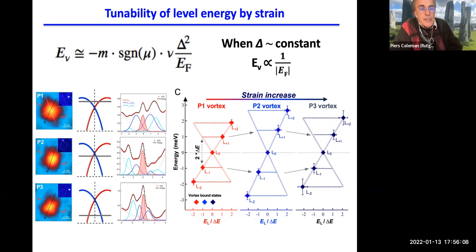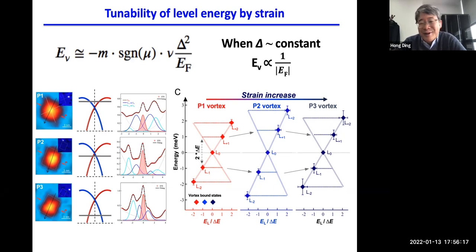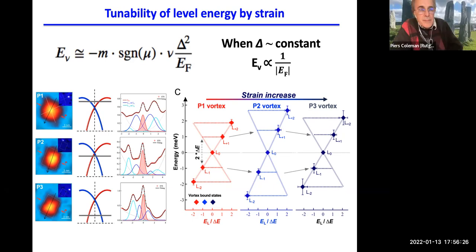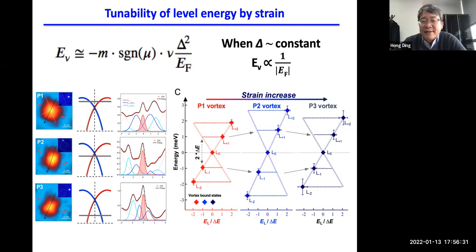Why does it fail in some vortices and not others? What is the variability that's there? In hindsight, now we look from the rear mirror, we understand. You have a different chemical potential for the different sites. Essentially, you have quite an inhomogeneous case, so the Majorana is very sensitive to the location of the chemical potential. As I showed in the case of lithium iron arsenic, in that case, you see 0% because you have a homogeneous case, which unfortunately has the EF sitting at this double crossing regime.